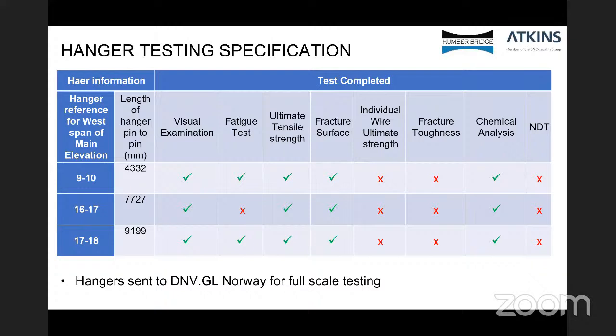Now, we did look at exploring the possibility of doing individual wire ultimate tensile strength to see if, similar to the NCHRP 5.3 report, we could rederive the hanger strengths from visual observations. However, it was decided after testing that wasn't necessary, so it was taken out of the scope. Again, fracture toughness, we hypothesized that perhaps fracture of the wires were controlling the failure mechanism, and for that reason, we would look at doing some fracture toughness evaluation. Again, that wasn't required after the initial test was carried out. All hangers were tested by DNV GL from Norway. We'll look on to the next slide.